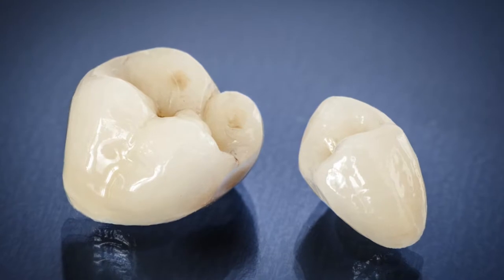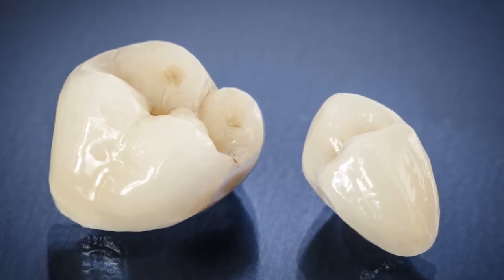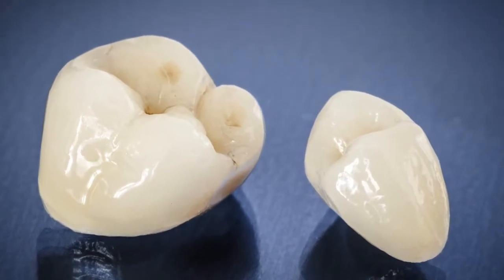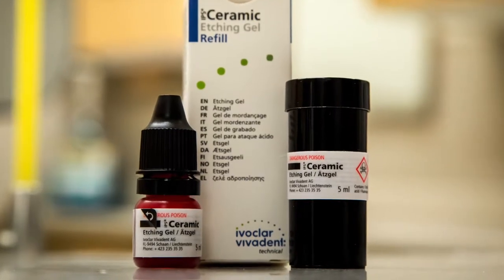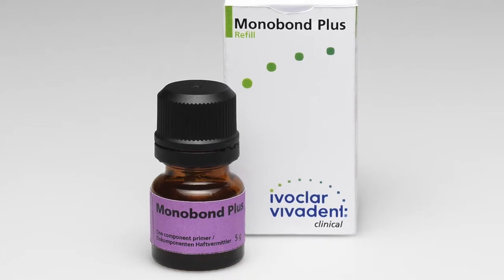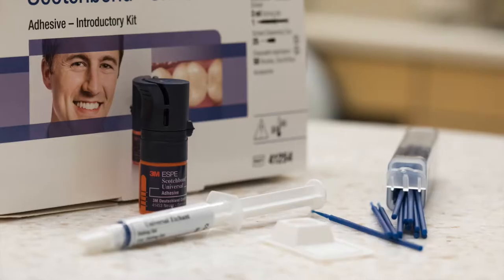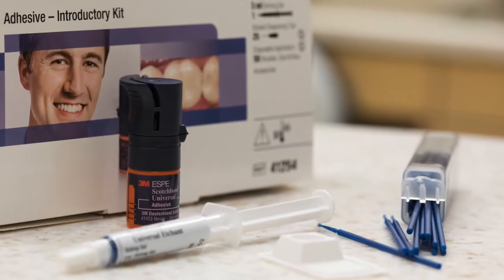Now, a recent study in the Journal of Prosthetic Dentistry actually demonstrated on a lithium disilicate crown, if you use a separate silane in addition to your universal adhesive, you get a better bond to the tooth. I'm going to recommend that you actually etch the crown with your hydrofluoric acid, then apply a separate silane to the crown, follow that up with your universal adhesive. Now, most of the universal adhesives do not require that you light cure the adhesive in the crown. You can actually just leave it as is, and then when you're ready to cement, you go ahead and cement the crown onto the tooth.